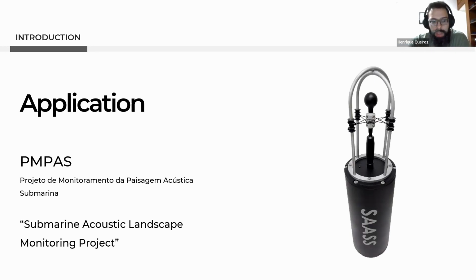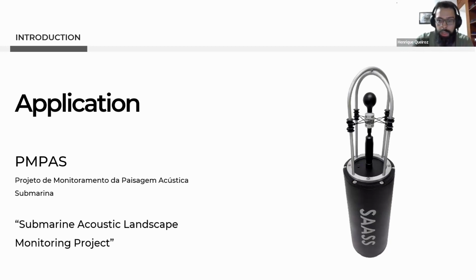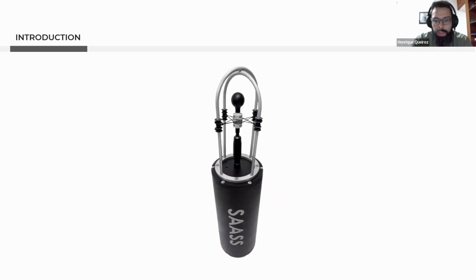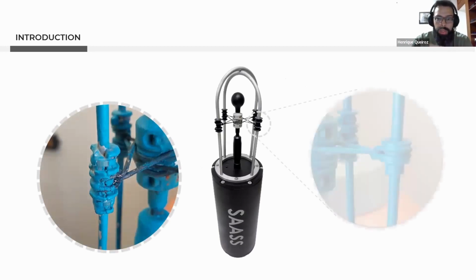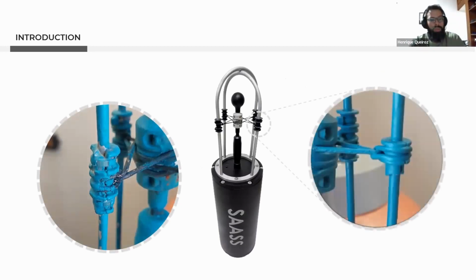And so they have a kind of sonar, right? They use, it's in the image right now to the right, and they use to have an acoustic monitoring of the landscape, right? And so they use this coupled with military projects, even in the petroleum industry, right? And so parts of the structure are 3D printed, have been 3D printed recently. And so what was observed is that the PLA printed parts, after long exposure to the marine environment, they come back deteriorated, right?